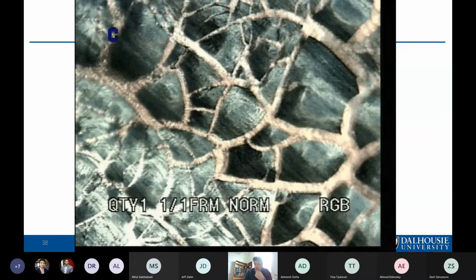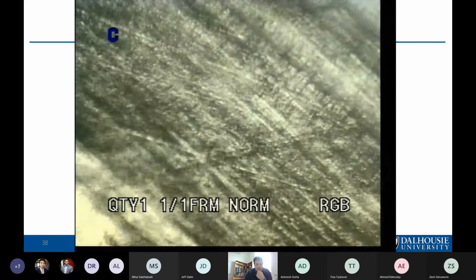There's no two-phase regions here. This is lithiating and delithiating in a single-phase region. And yeah, these are pinned by one point, one little foot, we called it, at the bottom of each one of these flakes. And after the initial cracking, then you could lithiate and delithiate these things reversibly back and forth.